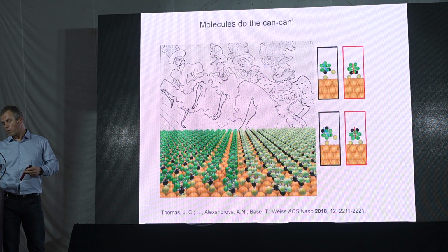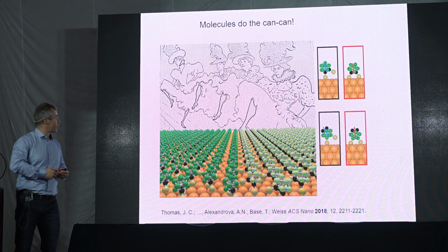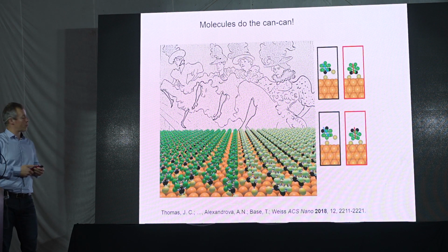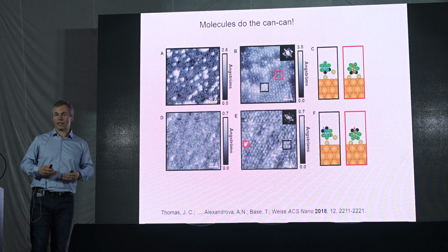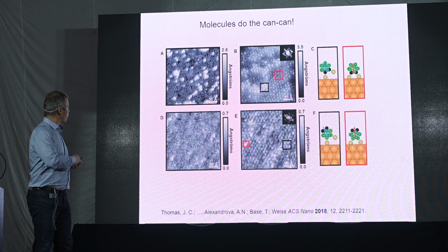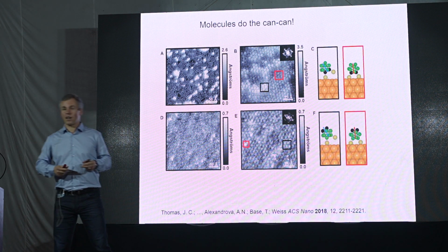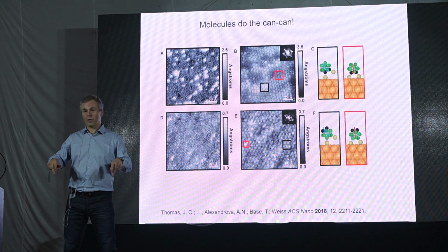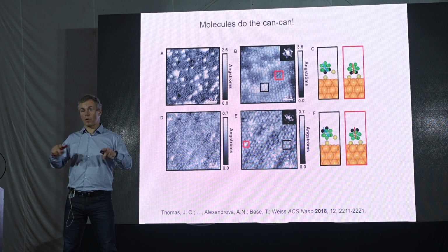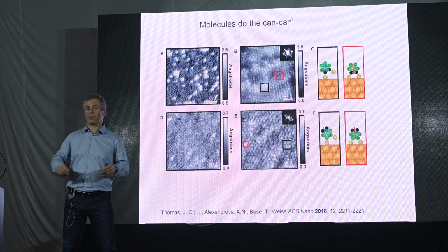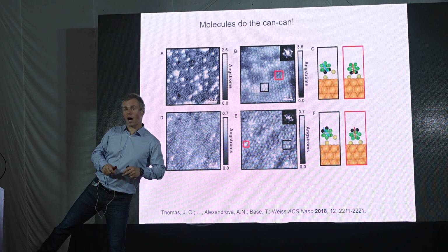And I'll show you now some chemistry of these molecules, which has been done with a friend of mine, Paul Weiss from UCLA, and we've looked at these molecules using a scanning tunneling microscope. We found that these molecules can be standing on the surface either with both legs as dithiolates, which means that both SH groups lose the proton, or one of them is sort of lifted up.